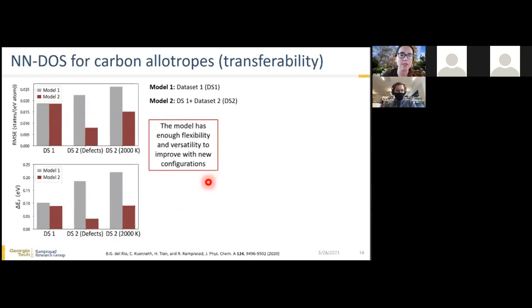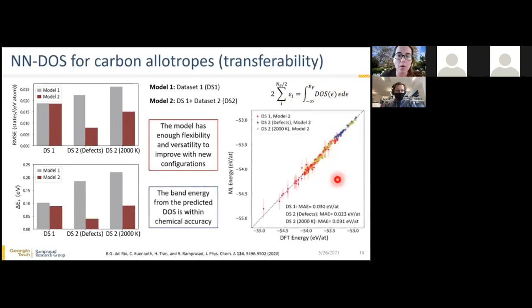And lastly, the band energy computed as the cumulative integral of the product between the level occupation and its energy up to the Fermi level has a mean absolute error below the chemical accuracy threshold for all cases, using model 2. So you can see that it's below 0.043 eV per atom, which would be 1 kilocalorie per mole, basically.